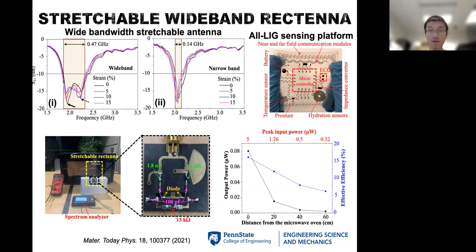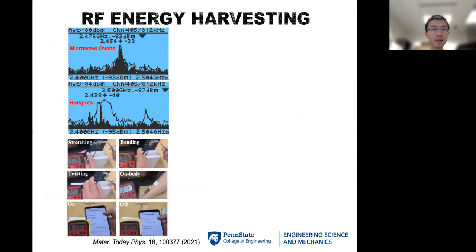And this is not that dramatic if you look at the number alone, but the theoretical limit to this conversion is about 0.3%, because the bare diode is not even turned on in most of the cases. So that's why the wideband antenna is super helpful. It can combine all the energy that is small, and integrate it together to get a much higher energy. So if we look at the energy spectrum from the microwave oven, from the hotspot of the smartphone, we'll be able to see it's not really at a single peak, but rather has energy distributed around it. So when we have the wide band, we can combine all the energy together and harvest that into DC power like 0.3, 0.4 volt from the environment.